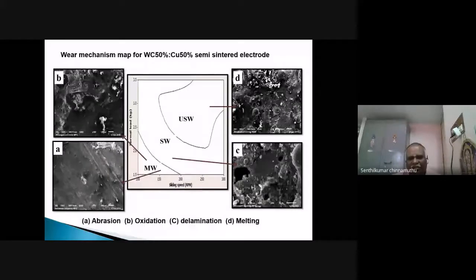And in the ultra severe wear zone, with further increase in the sliding speed and normal load, the contact between the tool and the pin and disc material is more, and the friction between the pin and the disc is also higher. Due to higher friction, the temperature increases and melting of the material takes place. Finally, the seizure occurs. So the mild wear region is the safest region for the design engineers.